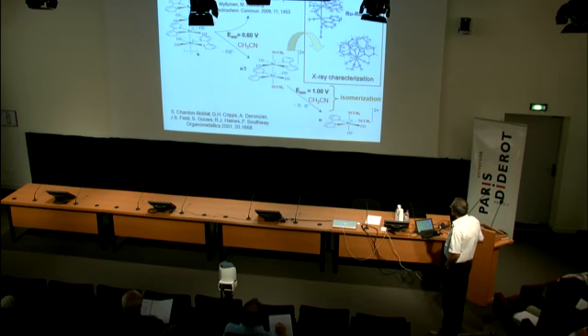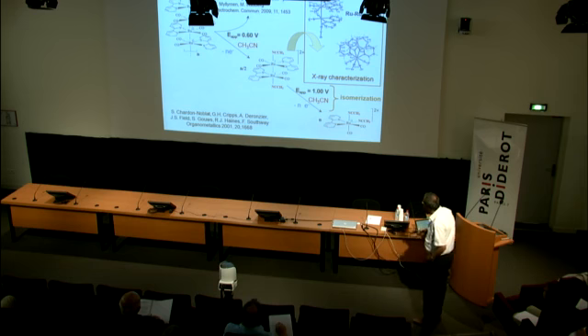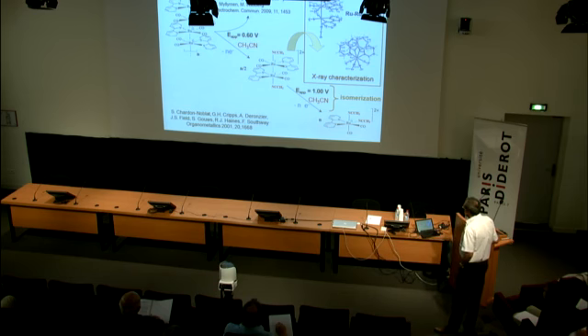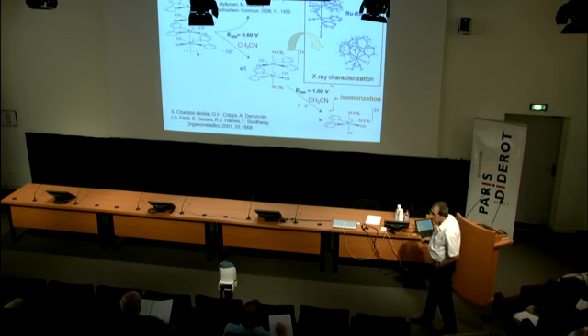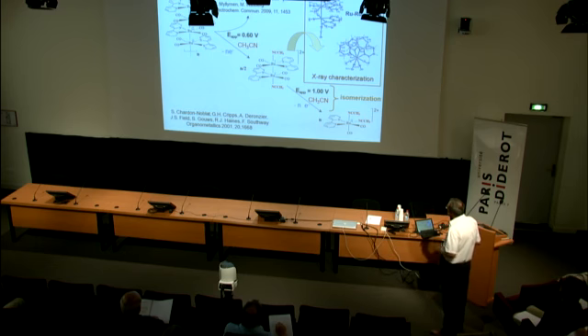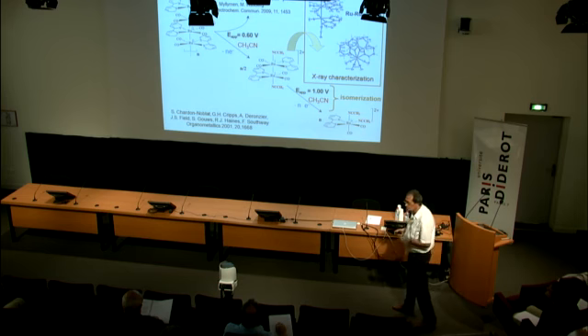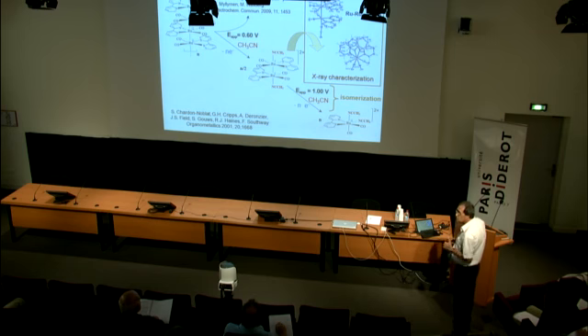The first one led to this dimer, the ruthenium-ruthenium metal-bonded system with the two acetonitriles in axial position, and the second step led to the bis-acetonitrile complex, and some isomerization occurs. I mean, in this case, you go back to the cis compound. It's a detail. More importantly, some other group at Turku University demonstrated very recently that the partially oxidized form of the polymer has a high electrical conductivity, and they studied in detail the structure of the film as a function of the potential.